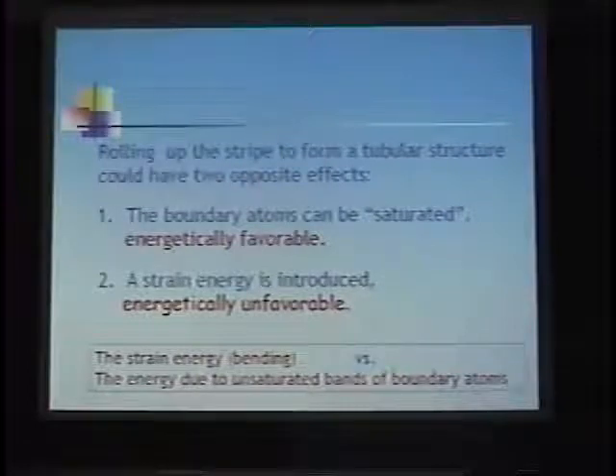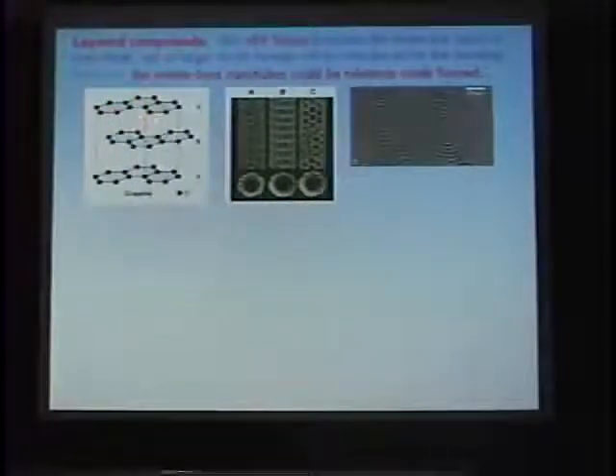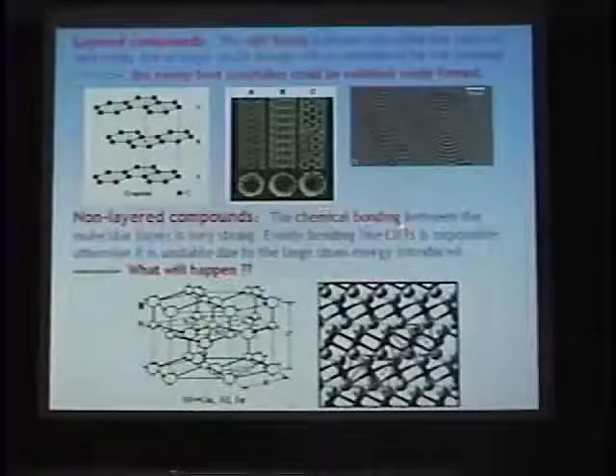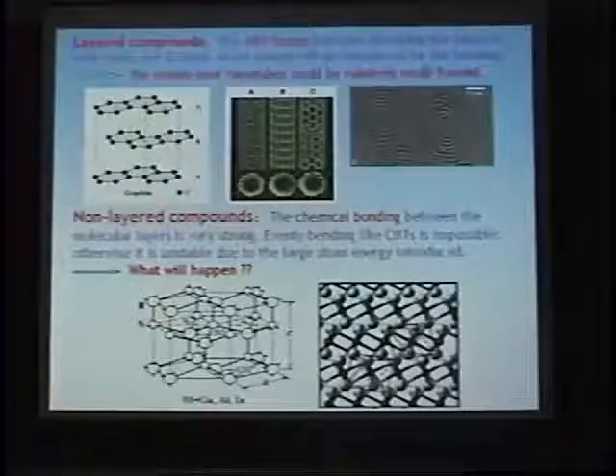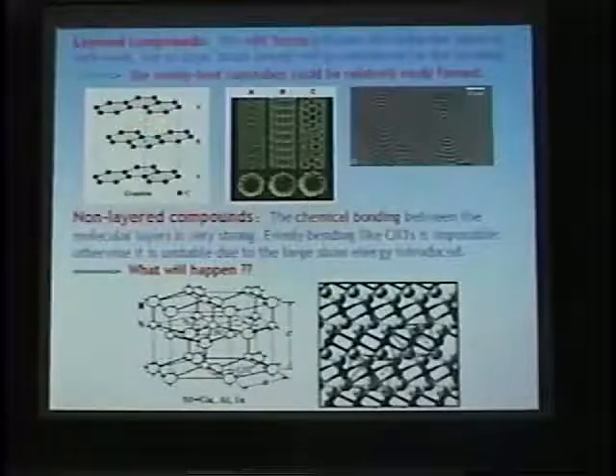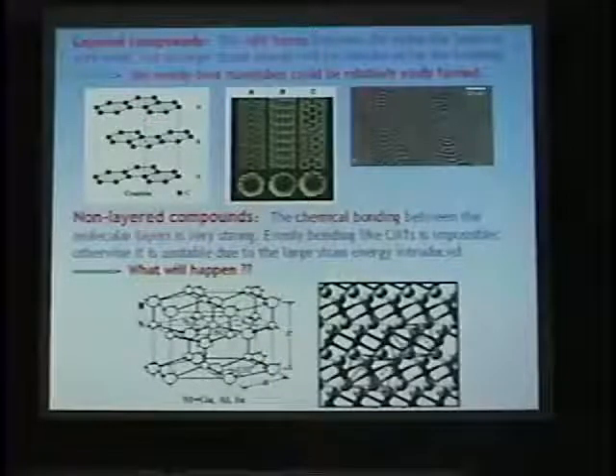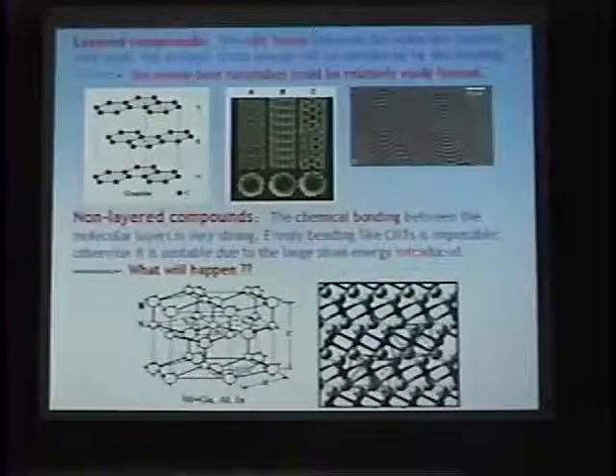So for the layered compounds, the van der Waals force between the molecular layers is very weak, so not so large an energy will be introduced by the bending. And so evenly bent nanotubes could be relatively easily formed. That's why we could prepare so many different kinds of nanotubes from layered compounds. However, for non-layered compounds, the chemical bond between the molecules is very strong. That means the van der Waals force is replaced by a chemical bond. Then an evenly bent structure like a carbon nanotube is impossible, otherwise it's unstable due to the large strain energy introduced.